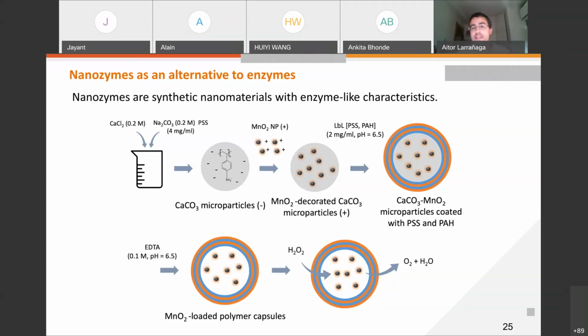So once we fabricated our manganese dioxide decorated calcium carbonate sacrificial template, we proceeded with the layer-by-layer approach, as I mentioned before, by simply incubating these particles alternately in positively and negatively charged polyelectrolytes. After coating these particles, we proceeded with the removal of the template. We did exactly the same as I mentioned before with EDTA in very mild conditions, finally leading to antioxidant microreactors loaded with manganese dioxide nanoparticles.